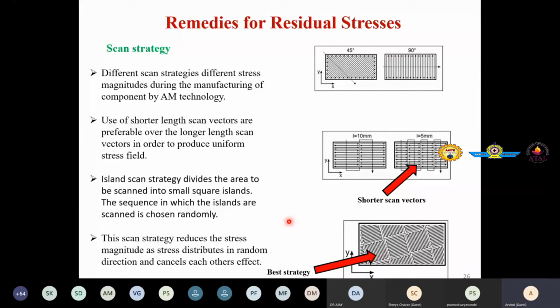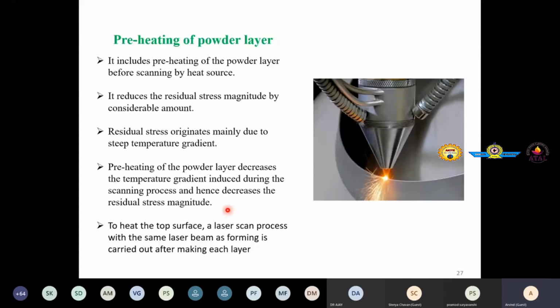So some other technique is preheating of the powder layer. It means that before starting the laser to scan a current layer, we preheat the powder layer, and preheating basically minimizes the temperature gradient. And if you minimize the temperature gradient, your thermal stress will be minimized, and as a result, you will not reach the threshold value. But in SLM, preheating is not very popular because it will extend the production cycle, and you have to use another laser for that. You cannot use IR heating and so on in the SLM process.